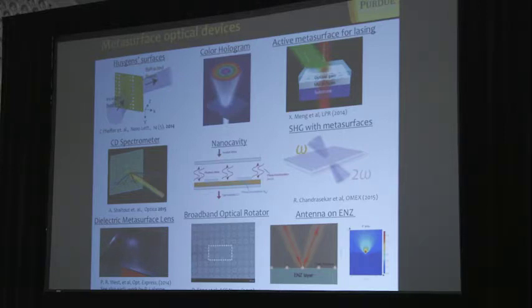You could make it out of dielectric if you would like to make losses smaller. I'm sure in our work, but there are many other works, including Philippe Lalanne, actually earlier than others, when people were using dielectric lenses. You could make a color hologram. You can make a cavity smaller than the wavelength. The basic idea behind a cavity feedback system is that the wavefront after one round trip should restore itself. And for that, the smallest size is lambda over 2, as we know. But if I have antennas here which introduce additional shift of phase, I could restore the phase front even if the size of the cavity is smaller than the wavelength. And we now have preliminary results that a cavity only 50 nanometers in size works as a regular cavity.